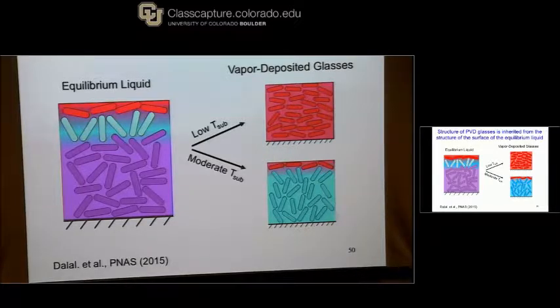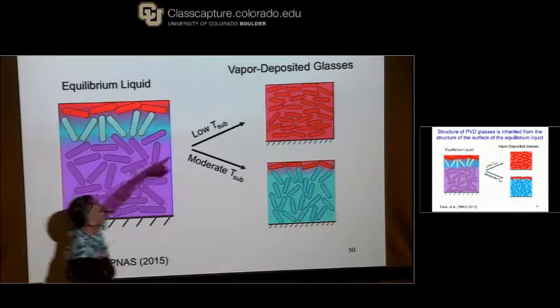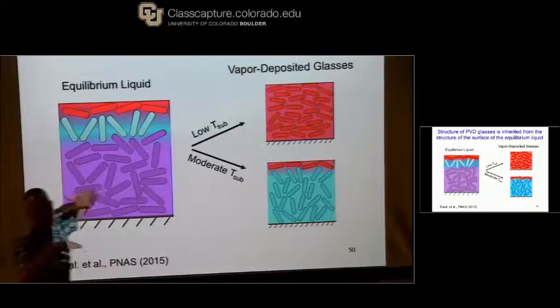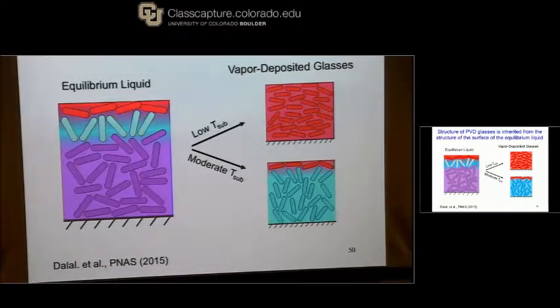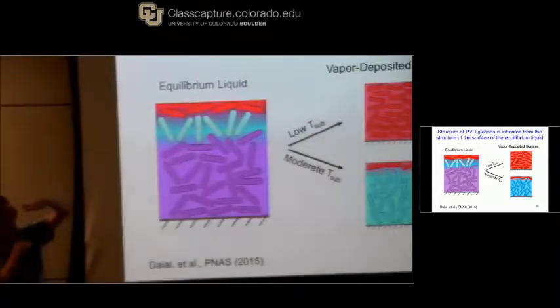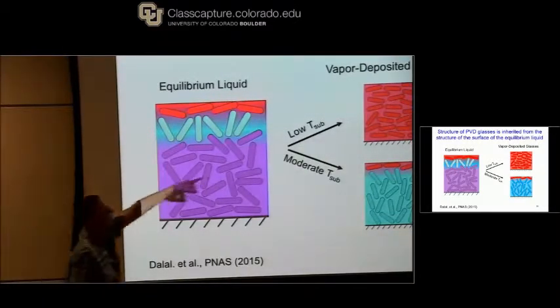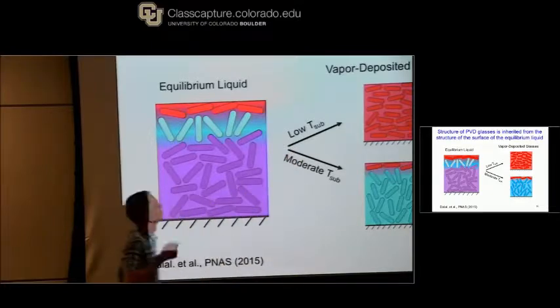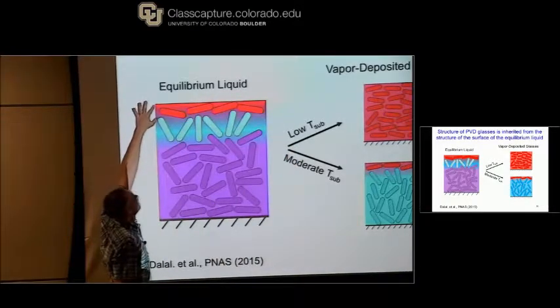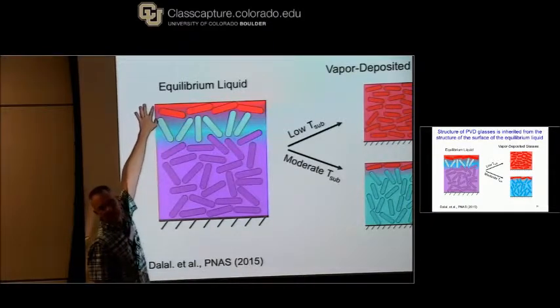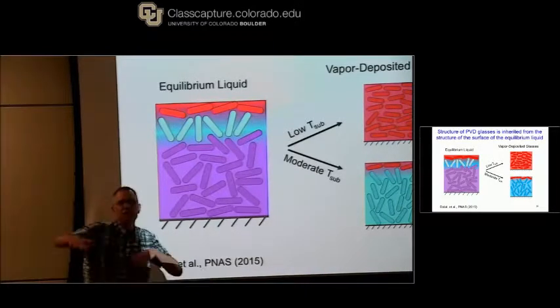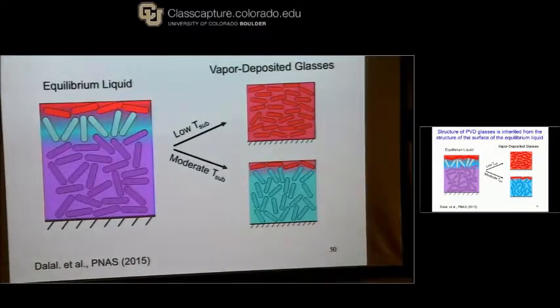Okay, but to the point, how does this tell me about the structure of vapor-deposited glasses? So I like this explanation a lot, even though it wasn't my idea. It was Juan's idea, and it came from the simulations. When you deposit at a low substrate temperature, there's not a lot of mobility. And of course, there's always going to be more mobility right at the free surface than anywhere else. So let's imagine that low substrate temperature means that at the deposition rate you've chosen, you only have enough time to equilibrate this very top layer. Okay? So then you're going to put that layer down, and then you're going to deposit more molecules.